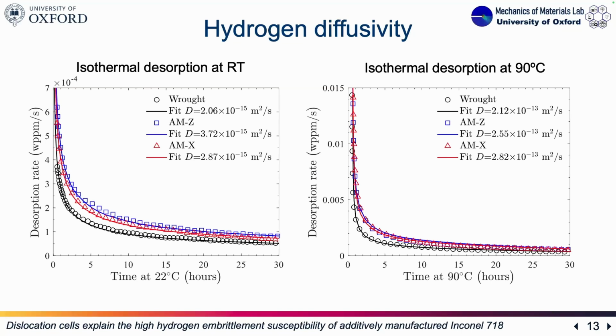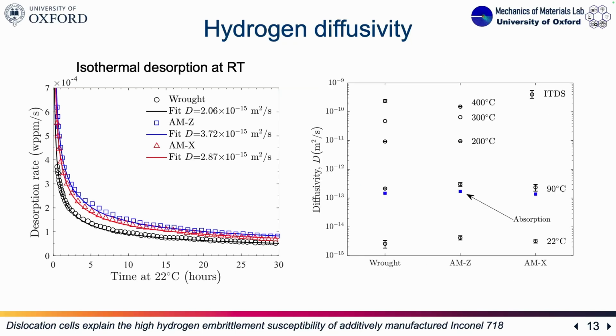So this is how the isothermal desorption spectra look. I've just shown 2 examples, at room temperature and 90 degrees, and the fittings. So we can see again, and actually we can see it better here, the diffusivity for the 3 conditions at different temperatures. In general, the diffusivity of the wrought and the additive is pretty comparable. We could say that maybe at lower temperatures, 90 and 22, the AM has a slightly higher diffusivity, but these differences cannot be noticed at higher temperatures.